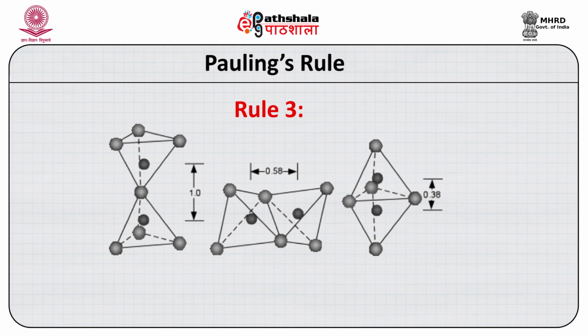Well, it is important also to recall the isodesmic and anisodesmic. There is also a category of bond described when the bond strength is nearly equal, that is called mesodesmic. Coming back to the polyhedral element sharing, the effect is large for cations with high valences and small coordination number. The example is that of carbon with 4 positive charge in 3-fold coordination, and it is especially large when the radius ratio approaches the lower limit of stability which we described in the table for a particular polyhedron.